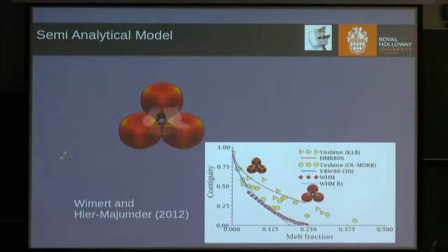Okay. So we have seen some results of Takashi Yoshino's earlier on. So this is a comparison of our results with von Bargen and Waff's model, which it fits quite well. The red diamonds are our data. Von Bargen and Waff, for these dihedral angles, reach their cutoff at about 19 volume percent melt. Our segregation happens at around 0.25 or 0.24.